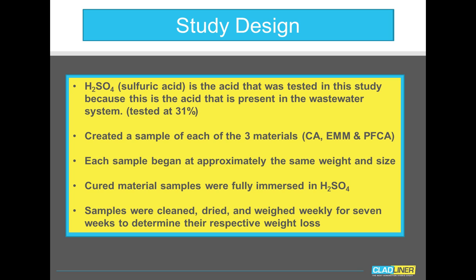Each sample was created to begin at approximately the same weight. Those weights were all within 1% of each other, so it was not a material difference in weight of the three core samples at the inception of the study. The cured samples were then immersed fully in the sulfuric acid mix. The samples were then removed, cleaned, dried, and weighed weekly for a period of 7 weeks, in order to determine their respective weight loss and the effect of the acidity on each one of the cores.